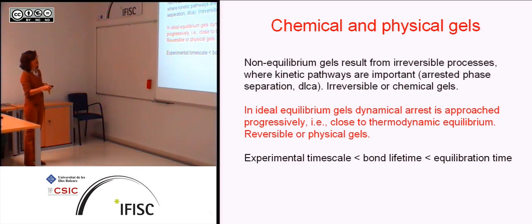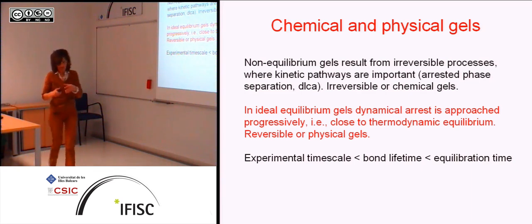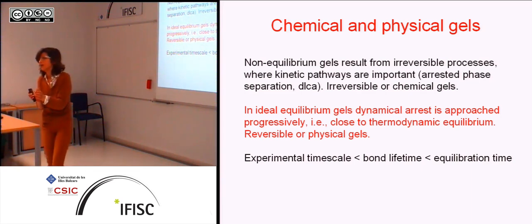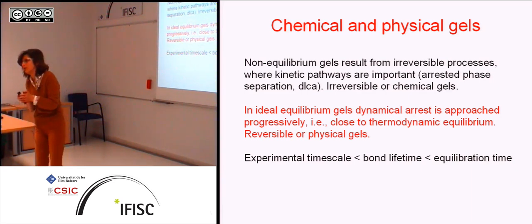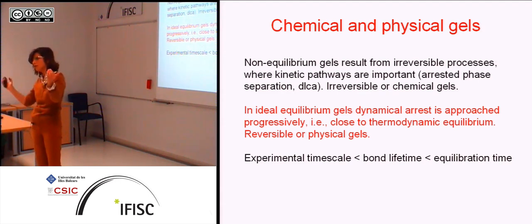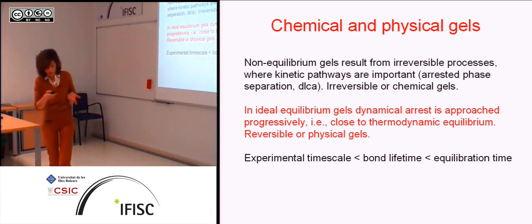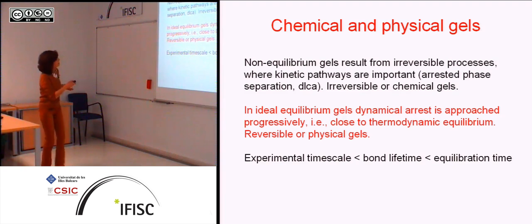And one mechanism, in fact, has been shown recently to be the generic mechanism to form gels without anisotropic interactions: an arrested phase separation. So you imagine your colloids, simple spherical colloids, try to phase separate into colloid-rich and colloid-poor, liquid and vapor. And if you arrest the phase separation, you form these gels that are totally out of equilibrium. Okay? So there are many other ways of doing that in models.